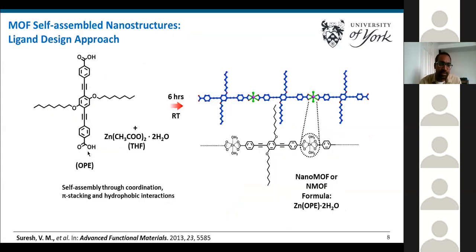The first example is based on this organic linker, which is called OPE. OPE is a rigid rod-like molecule with an extended pi conjugation, so it is highly emissive. This OPE linker is rationally designed and functionalized with terminal carboxylic acid groups, so it can bind to the metal ion. And it is functionalized with alkyl chains on both sides, which will control the nanomorphology that we obtain.